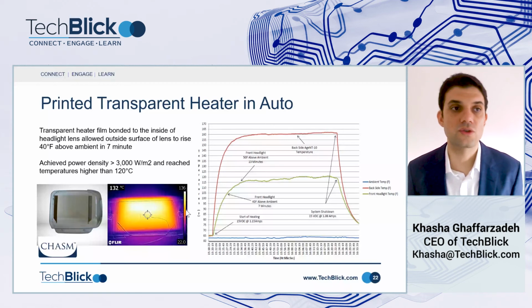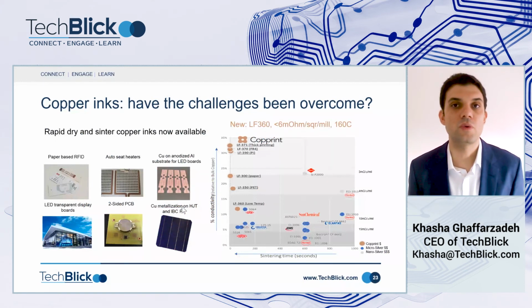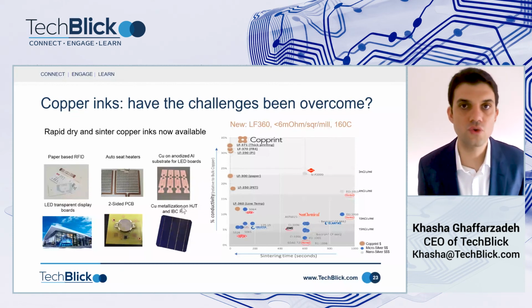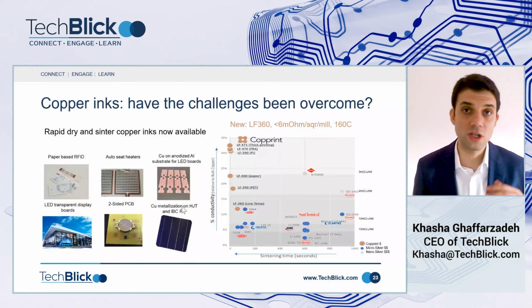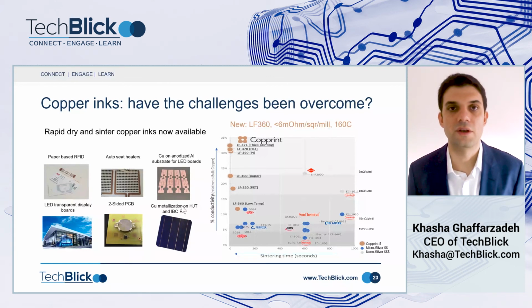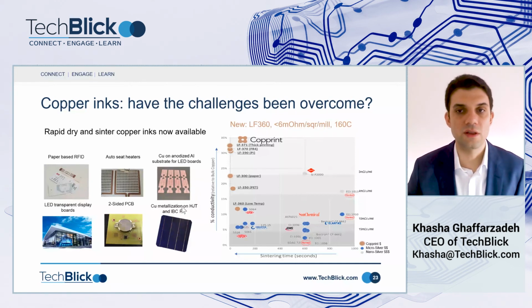Of course, the story of printed electronics and copper are intertwined, and conductive inks are intertwined. And for many years, people have tried to create copper inks to replace the expensive silver without so much success. And there have been two major problems. One of them has been the curing without oxidization, so special equipment or conditions were required, often adding expense, and also making copper not a drop-in replacement. And another problem has been that copper wasn't conductive enough, so you would end up printing such a thick layer that you would make your cost benefits disappear. Now there are some coppers appearing on the market which seem very promising, and one example I want to highlight is by Copprint out of Israel. And you can see their own benchmarking.